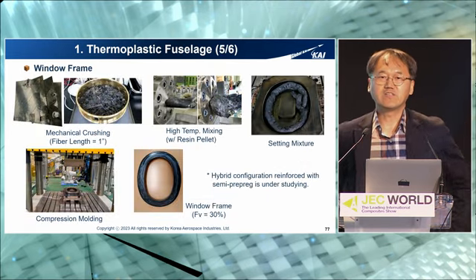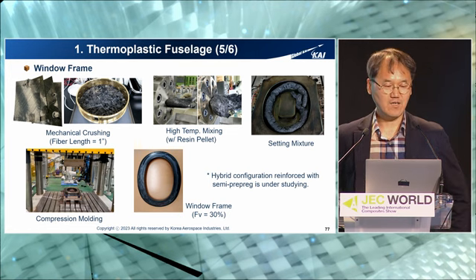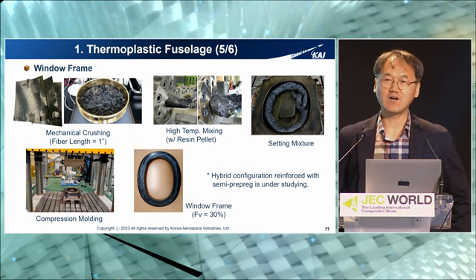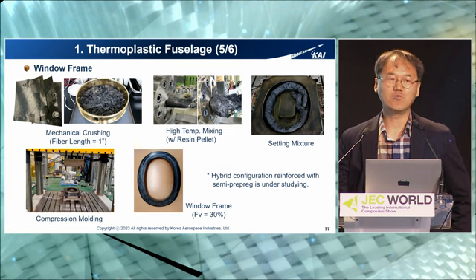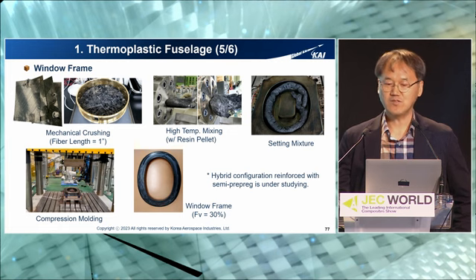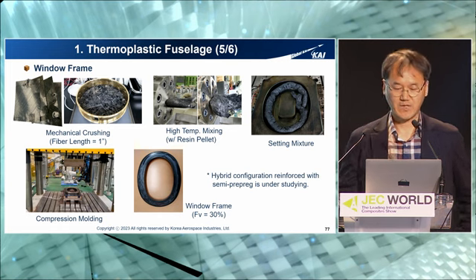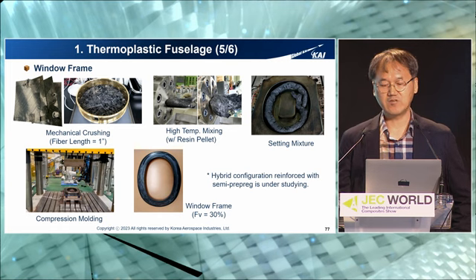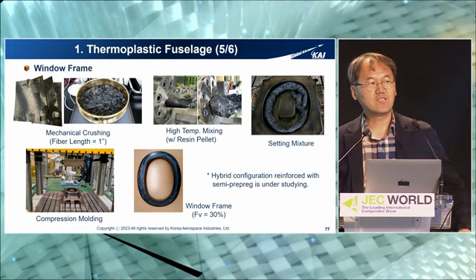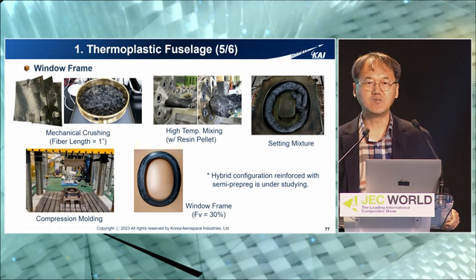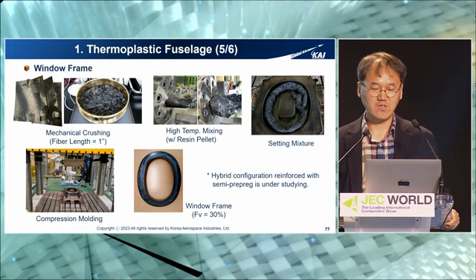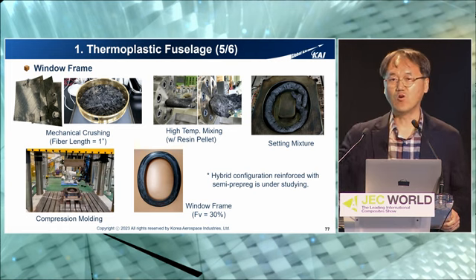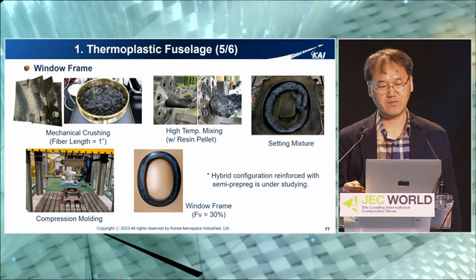As I mentioned, for the eco-friendly manufacturing technology, we shredded and crushed the previously consolidated parts to make recycled material with approximately 1-inch fiber length, and we added extra resin pellets to give more viscosity when you heat the mix. And finally, we got a 30% fiber volume window frame, and currently, to give more structural reinforcement, we are starting to apply the same semi-prepreg material over the window frame structure.